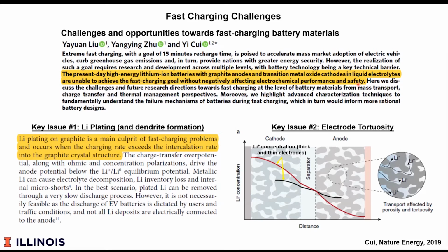And so what do I see as really the two key issues? If we had to elevate and say, what must we solve fundamentally for all of the other factors to then become important? The key issue in fast charging is lithium plating and dendrite formation. So even if we go to a system that contains a metal anode, which is a major goal of the field, if that anode grows too quickly, it will not grow uniformly, but rather lithium dendrites will grow into the electrolyte. And at least up to today, those dendrites have the mechanical properties such that they will eventually crack through the electrolyte, even if it's a solid electrolyte.